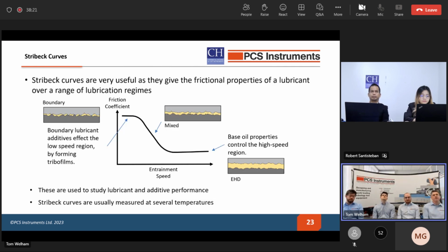So firstly, in more detail about the Stribeck curves, they can be really useful because by varying the entrainment speed, we can look at how the lubricant behaves in the different lubrication regimes. So at high speed, we're around here in the full EHD region. So this is where the oil itself is supporting the contact. So there's no metal to metal contact, and so it's the base oil properties that are controlling the amount of friction in the contact.